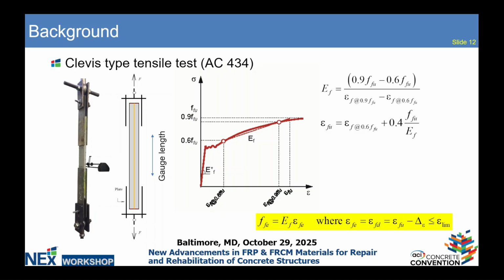And eventually, again, the effective strain is basically the epsilon FU that I just talked about minus the standard deviation. And from that, and the elastic modulus, you can get the stress of the composite in design. So if you do your calculation, 0.4 FFU, you get the horizontal line. Then you take 0.6 FU, the epsilon, and you follow the second equation of the epsilon. You will see that this is the epsilon FU.